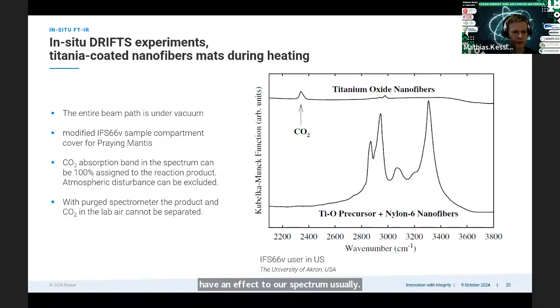There are other experiments which can be done in such cells. We can, of course, do a real reaction. If we have a titanium oxide precursor and react it with a nylon nanofiber, we can observe and track this reaction during the process. And finally, we are then able to observe the products. So our titanium oxide nanofibers and also the carbon dioxide, which is released during that process. And again, with a vacuum spectrometer, we are sure that this carbon dioxide comes from the reaction itself and is not a part of the atmosphere in the lab.